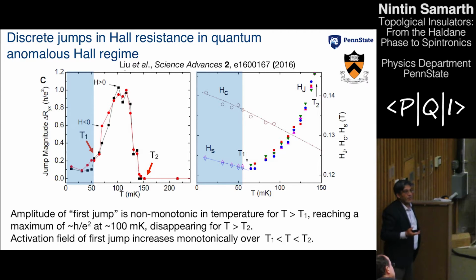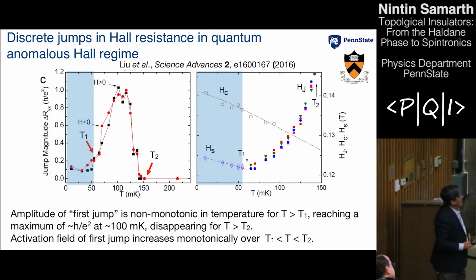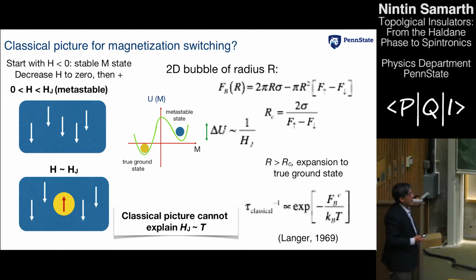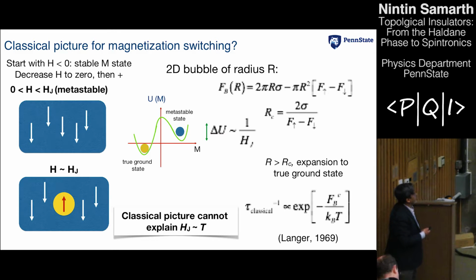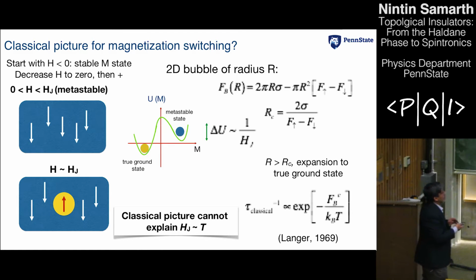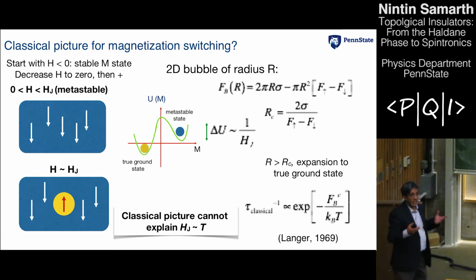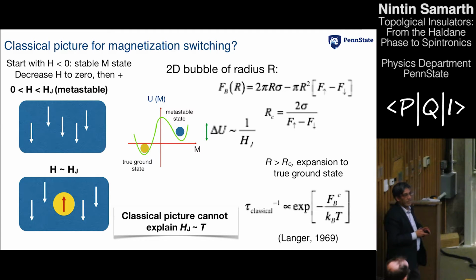Now, these are the two parameters we have to play with, and this is the temperature dependence that we have to play with. So you can start asking yourself, well, can this be explained in some simple classical model? And you can try developing some simple classical model in which you say to yourself that, well, when I bring my field from negative values through 0, and I cross the 0 value of magnetic field, I'm going to be in some metastable state where the magnetization moments are still pointing in the direction that the magnetic field was earlier. And then as I start approaching this jump field, I'm going to nucleate some bubble of magnetization, and that bubble of magnetization will grow, right? So you can try to analyze this by using a simple two-dimensional model, an analogy in some sense, in which the surface tension of a bubble is connected to the exchange energy in the problem. And you can try to then develop a simple model in which you try to understand how the expansion of this bubble might be explained in a classical sense.